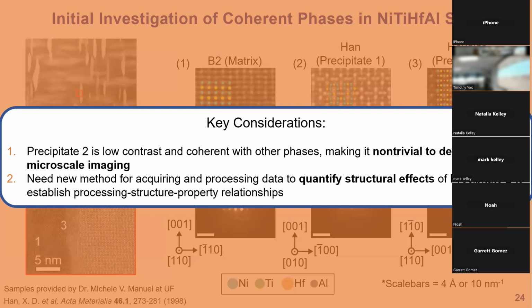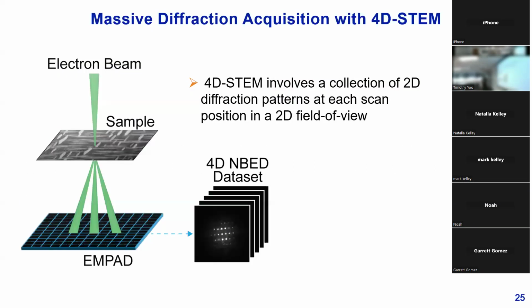And so just to reiterate, the key consideration here is that precipitate 2 in particular is very low in contrast, and also all 3 phases are completely coherent with each other, making it non-trivial in terms of image processing. We also need a new method for acquiring and processing data, specifically diffraction data, in order to quantify the structural effects of the precipitate formation in order to establish proper structure-processing-property relationships. And so how we can acquire this data is by using a relatively modern technique called 4-dimensional STEM.